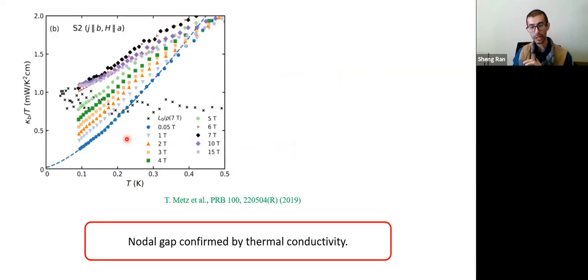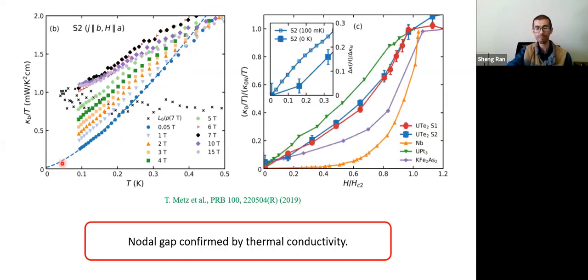All right, we can do thermal conductivity to look at the energy gap a little bit more carefully. Again, if this is a BCS type of superconductor, this quantity should go to 0 exponentially. But here it's parallel. And again, this is consistent with a node on the gap. But all of this is not the most exciting part. The most exciting part comes when we put this under magnetic field.